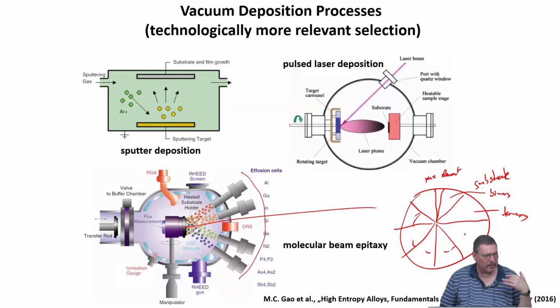And then it gets more complicated. People are thinking also about doing, for example, EDS automatically in an SEM on these structures, maybe even going to TEM level. So far I have not seen it, but people were discussing this. So you get the full information, or rather a large range of information. You could have nano indentation also done automatically on already a huge range of compositions and never breaking the vacuum. This is important. Point is, problem with thin films comparing to bulk structures again, right? So this is valuable information for thin films, but how to really extract valuable information for your bulk alloys is something we have to always worry about, because it will depend also on the specific material under investigation.